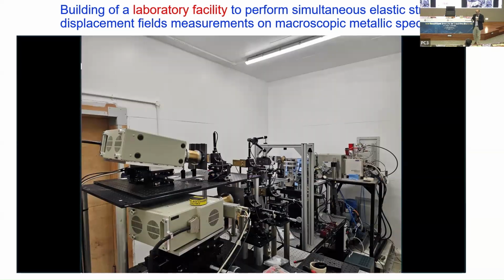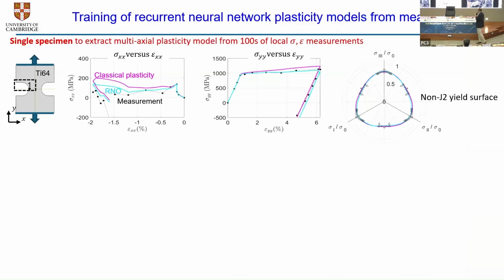And that's what it actually looks like, okay? It doesn't look as fancy as that movie, but that's what it actually looks like. So that's what we have done, and so this is what you can get. For example, if we have this kind of a notch specimen, at the root of the notch we're going to get these kinds of multi-axial stress strain curves.